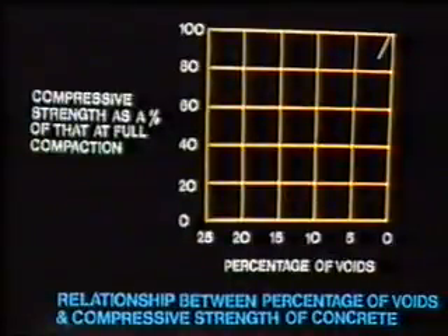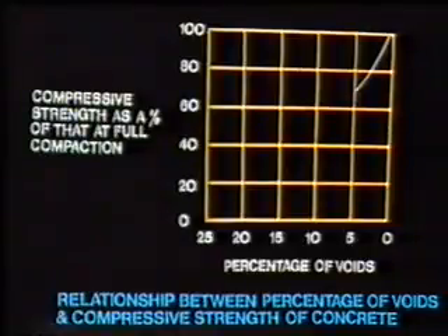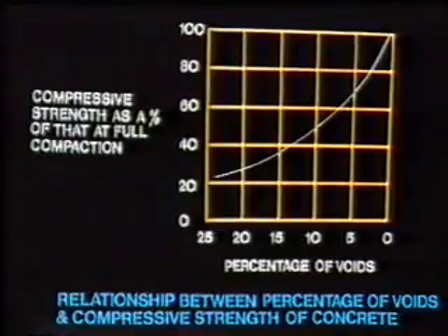Good workability results in much better compaction and hence dense concrete with minimum air voids. From the graph, it's evident that due to lack of compaction, even 5% air voids in plastic concrete results in 33% reduction in strength. 10% air voids in plastic concrete results in 55% reduction in strength of hardened concrete. Thus, the workability of concrete in the plastic stage is of utmost importance in compaction of concrete and ultimately in achieving the desired strength and other qualities of concrete.